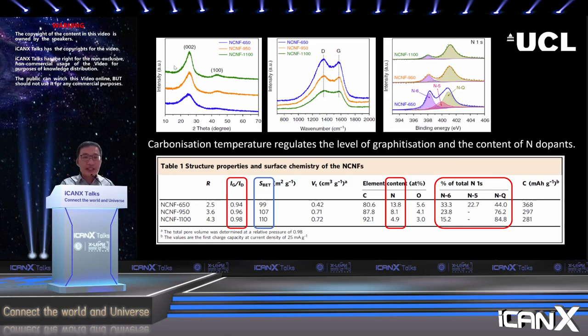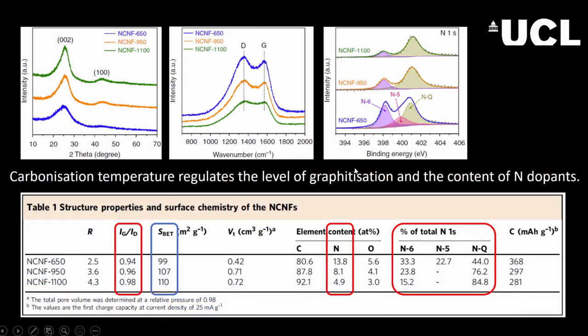From XRD and the Raman technology, we understand that by increasing the carbonization temperature, the level of graphitization increases, which means the carbon defects decrease. We also use the XPS characterization to identify the types and the content of nitrogen doping inside the three different types of the samples. So we use a little bit of calculation to identify the level of graphitization, and we tested the surface area of the three samples, which actually doesn't show much difference among them.